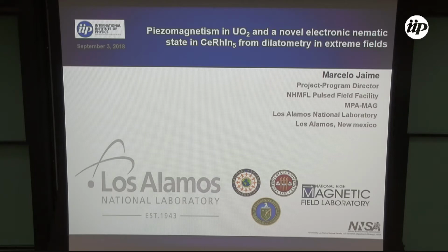This is the noise of a transformer. When you're waiting for the bus in the street or close to your apartment in the city, there is a power transformer nearby, and this is what happens in different tones. This is caused by a phenomenon of piezomagnetism in part. When you have a transformer and an iron core, the iron core vibrates at the frequency of the AC current in the transformer. And this vibration is transmitted to the case of the transformer and very often amplified to the point that you want to turn that thing down because it's driving you nuts.